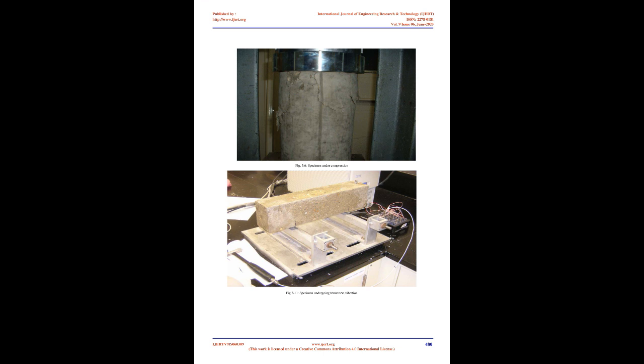Under the sponsorship of the New Jersey Department of Transportation, a unique concrete mix was developed. This concrete mix attained a significant strength of 3,000 to 3,500 psi, 21 to 24.5 MPa, in a period of 6 to 9 hours for use on pavement repair in high-traffic areas. FHWA New Jersey 2001-015. The use of normal Portland cement and the reliance on chemical admixtures and insulated coverings was used to attain very high temperature levels in order to attain early strength.